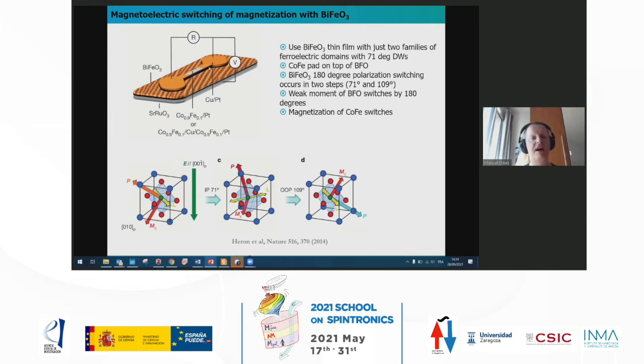So he worked with bismuth ferrite, and then he has cobalt iron on top. And then he makes these GMR layers with a copper spacer and then another cobalt iron layer. And then he takes advantage of a specific switching process of polarization in bismuth ferrite, which is called a two-step switching process, which in principle allows to switch the magnetization, the weak moment of the bismuth ferrite, because bismuth ferrite is an antiferromagnet. I mean, it's a complicated antiferromagnet because it has a spin cycloid, etc. But you can, for simplicity, assume it's an antiferromagnet, but it also has a small weak moment.